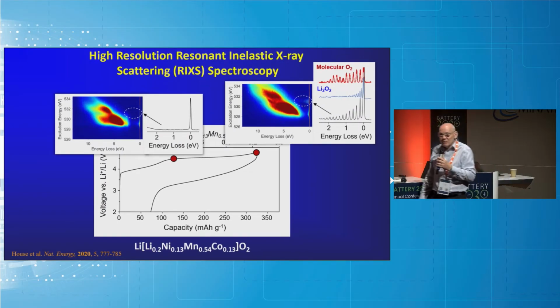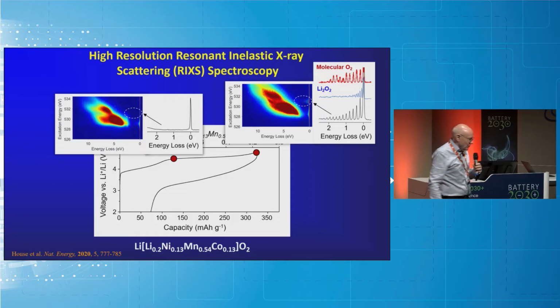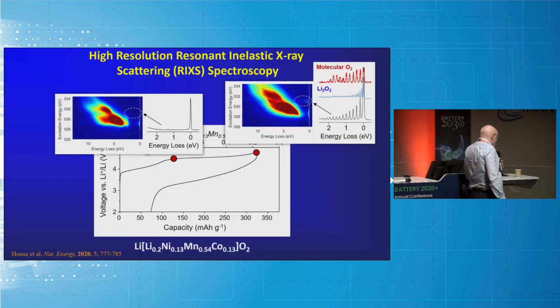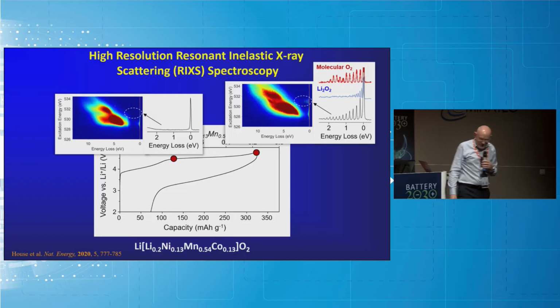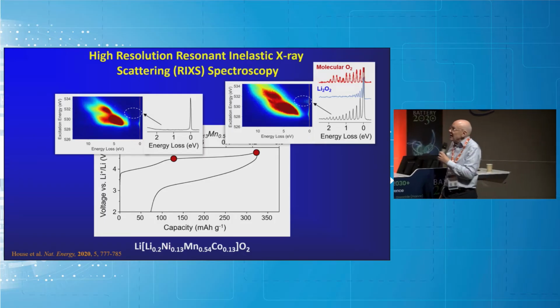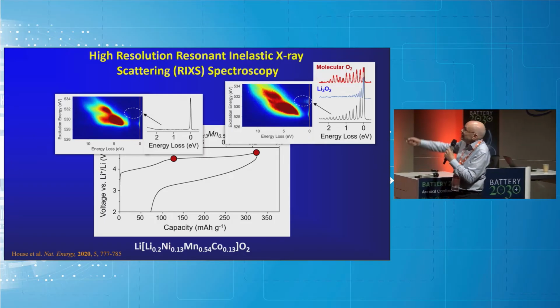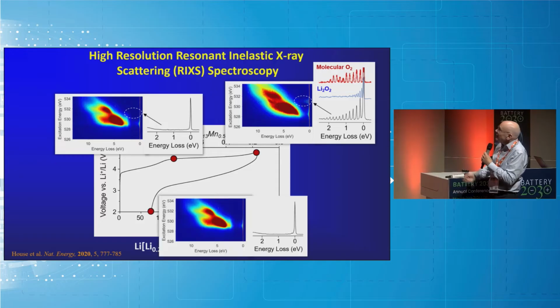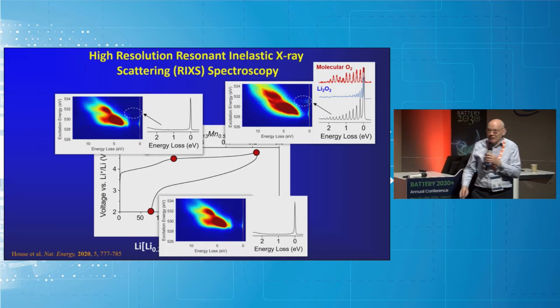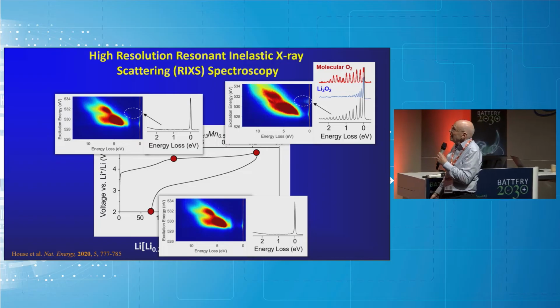Now, this is a high vacuum technique. This is not oxygen in the gas phase that we're seeing. This is oxygen inside the particles of the charged cathode material at the end of charge. And then when you discharge again, here's that blown up region, nothing is left. You're reducing that molecular oxygen again back to oxide ions.